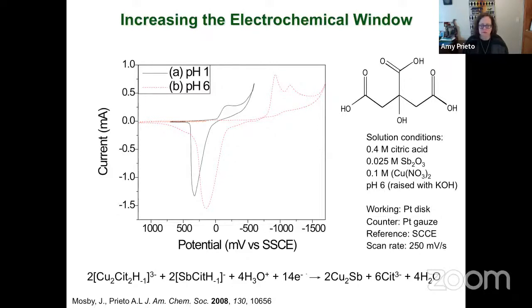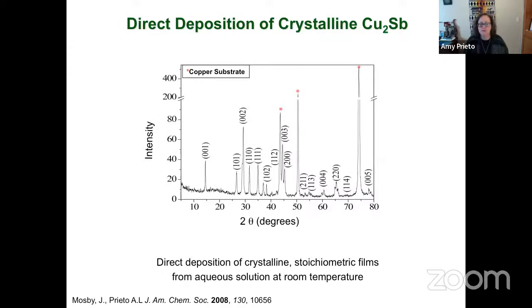The advantage of using citric acid is as you raise the pH, you can keep the antimony in solution. The electrochemical window shifts to much more negative potentials. And if you look at the two red peaks on the top right corner of the CV, if you hold your potential there, you can directly electrodeposit crystalline copper antimonide. So this is an X-ray diffraction pattern of a film that was deposited in 2 minutes. And again, it's just anomalous. It's so beautifully crystalline, deposited out of solution at room temperature.